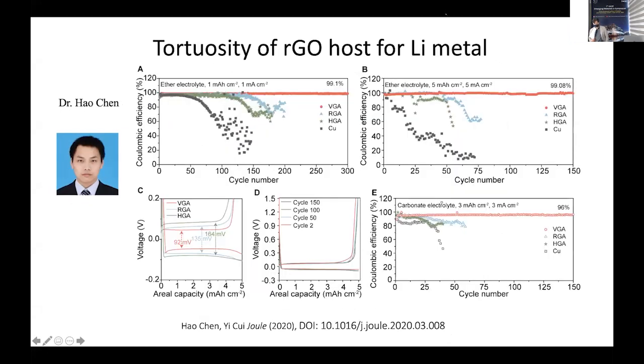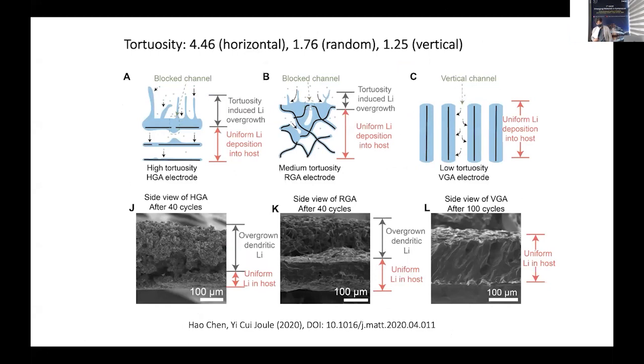If you look at the red color plot, that's the vertically aligned Coulombic efficiency and stability. The vertically aligned is better than the random aligned. Random is better than the horizontally aligned. It's actually a very, very strong correlation right there. And from the morphology, if you look at the top row of SEM, from the horizontal align, random align, to the right-hand side, vertically aligned graphene oxide, VGA has this dense lithium plating going into the graphene oxide, reducing the surface area of lithium metal, reducing so-called mossy lithium, and the stability of the vertical align is better.